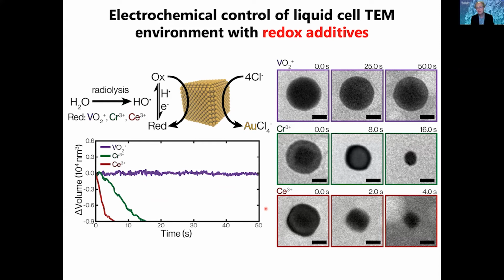So now we can take here a nanoparticle, let's say, and we can simply observe that nanoparticle of gold being etched. And we can do that either with vanadium oxide, the chromium, or the cerium. And I think what you can see very clearly is that in the presence of the cerium redox couple, we get a very rapid oxidation of the gold. It disappears very, very quickly.